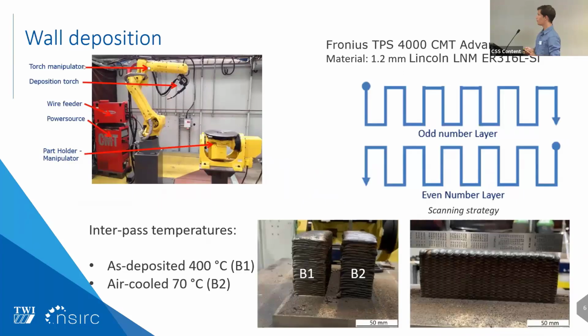So a bit about the experimental setup. I've deposited 2 walls to extract samples from and do the testing on. I used conventional welding wire described here - it's a welding wire typically used to join 2 stainless steel plates using an Si-enriched stainless steel alloy.